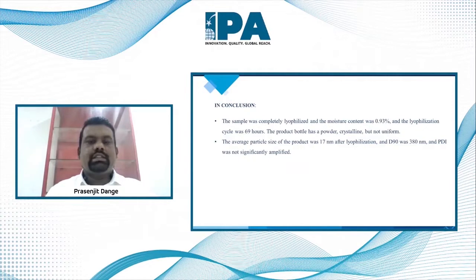The conclusion is the sample was completely lyophilized, and the moisture content was 0.93%. The lyophilization cycle was 69 hours in total. The product in the vial was a powder, crystalline but not uniform in this case. The average particle size of the product was 17 nanometers after lyophilization, D90 was 380 nm, and PDI was not significantly amplified. So these were the results of the first recipe. With this result, the average particle size of the product after freeze drying was greater than the customer demand. So we adapted another cycle, where we focused on supercooling and quick freezing mode. Can you go to the next slide?